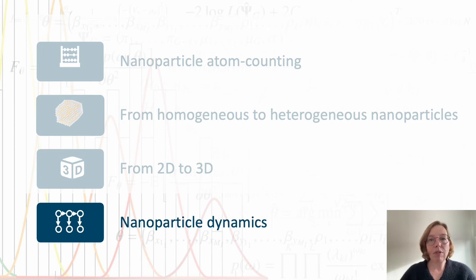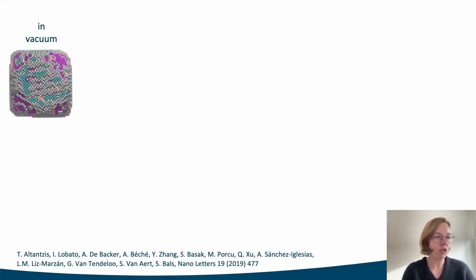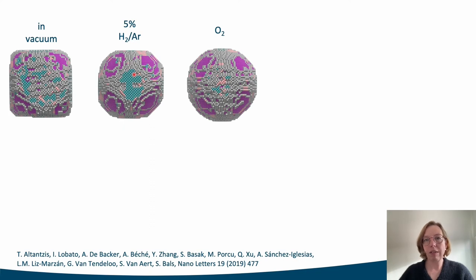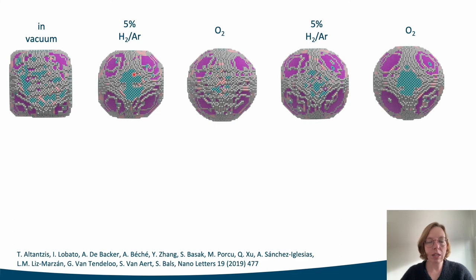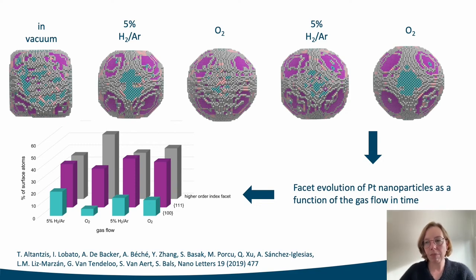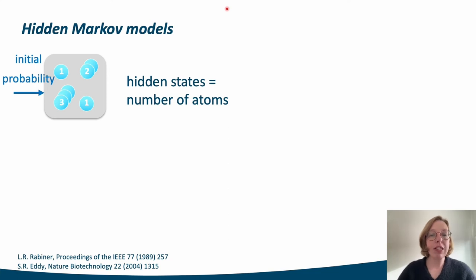This methodology of retrieving the 3D atomic structure from a single image opens up new prospects for analyzing in-situ experiments and tracking changes over time. Here you see the 3D reconstruction of a platinum nanoparticle in vacuum. More interestingly, we can now follow changes of such particles under the flow of selected gases — hydrogen and oxygen in this example — switching the gas flow and enabling us to quantify refaceting of platinum nanoparticles with atomic resolution during various cycles. In this example we obtained the 3D atomic structure by analyzing the underlying images frame by frame. One challenge now is to investigate if we can enhance reliability by modeling the dynamics between successive frames using a so-called hidden Markov model.